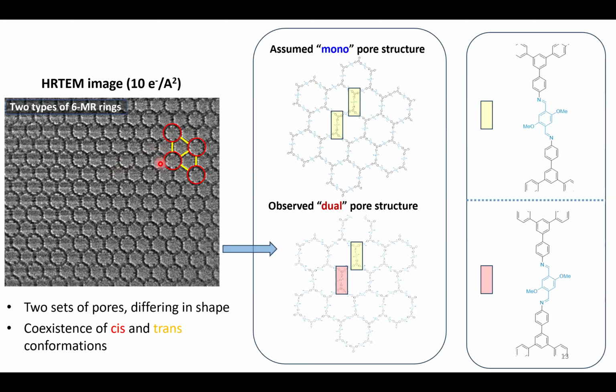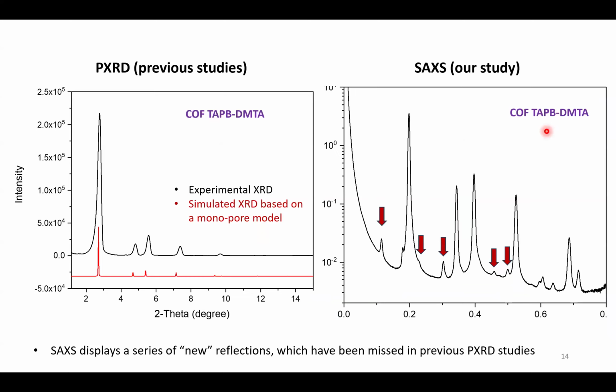To distinguish these two structures, we refer to the structure that people previously believed as a monopore structure, and what we actually observed in the TEM image as a dual-pore structure. A plausible explanation for the formation of a dual-pore structure is that the cis and the trans conformations of the diimine linkage coexist in the structure, which correspond to the curved and the straight edges respectively. In contrast, in the conventional structure model, people believe that this material contains only the trans conformation of the diimine bonds. So if our dual-pore model is correct, there should be diffraction peaks at low angle regions, right? Because of its larger unit cell.